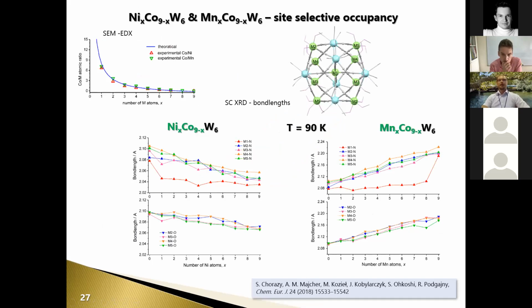Okay, and now we come to the series which has no phase transition: nickel, cobalt, tungsten, and manganese, cobalt, tungsten. What is the most important outcome of this research is that we have the preference of occupation of the central site with the metal ion with smaller distance, with smaller bond length, due to ligand field stabilization energy. We know that for nickel, this term should be the largest one.